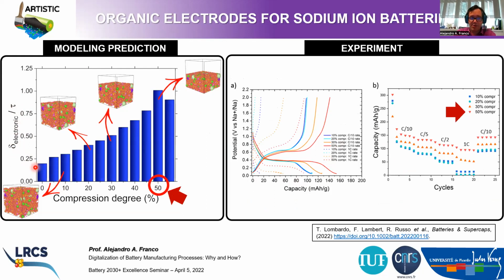And you see that the model predicts that when you increase the compression degree, this ratio will start to increase because the electronic conductivity gets better and better as you percolate the particles more and more. But then you reach an optimum, because here you are dividing by the tortuosity factor. That means that if you compress too much, the tortuosity factor becomes higher and higher with the compression degree, and at some point will become too high. The penalty from this increase of the tortuosity factor will overcome the benefit on the electronic conductivity from compressing the electrode. This is why, from the modeling point of view, if you keep compressing, this ratio will decrease. The model also says, which I'm not showing here, that you cannot compress more, because then the simulation becomes unstable. Particles are moving in a crazy way. Somehow we are reaching the physical limit of the model.